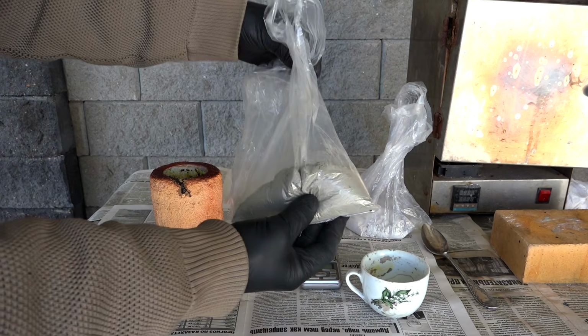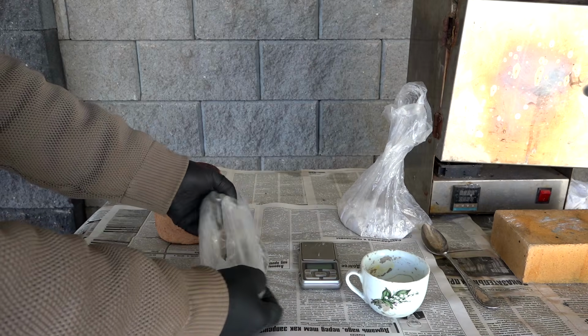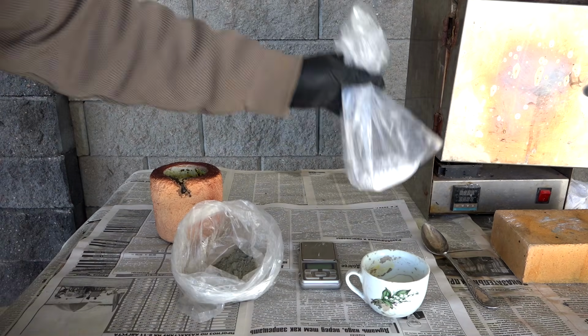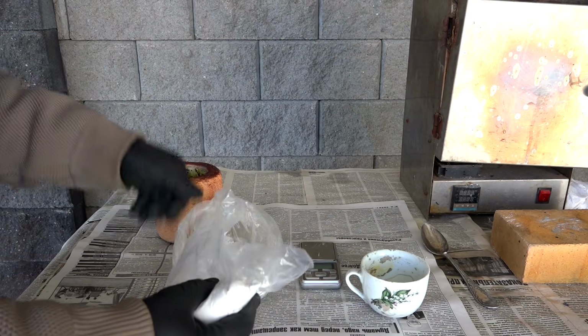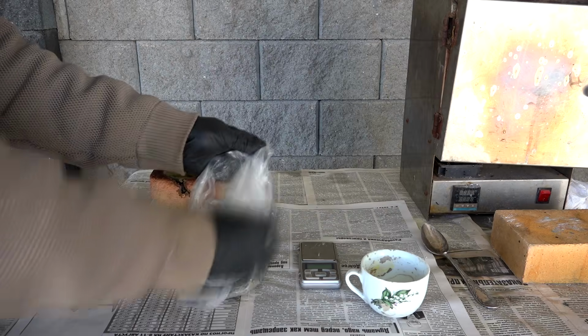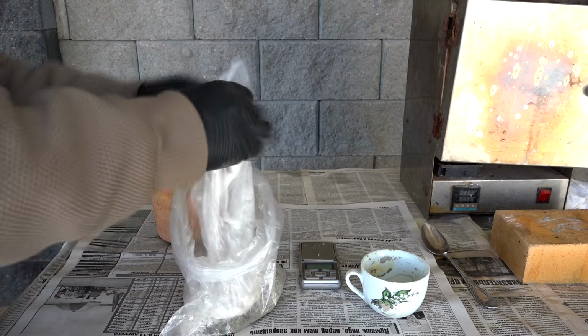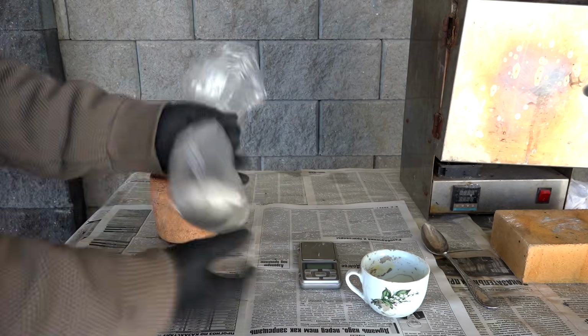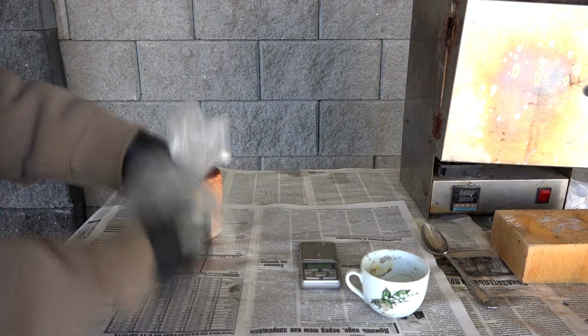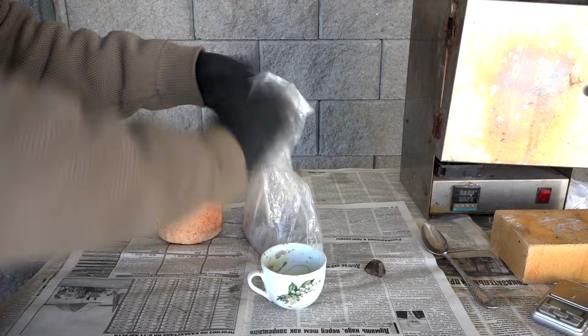Now I'll make a simple cupel out of cement and plaster. I'll simply mix these two free-flowing mixtures half and half and tamp the mixture with my hands in a ceramic cup, creating a sort of crucible. Plaster and cement absorb lead oxide well, leaving only the precious metal.